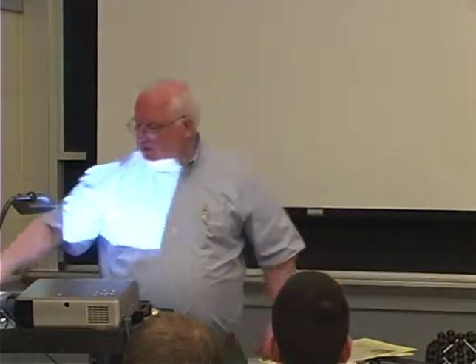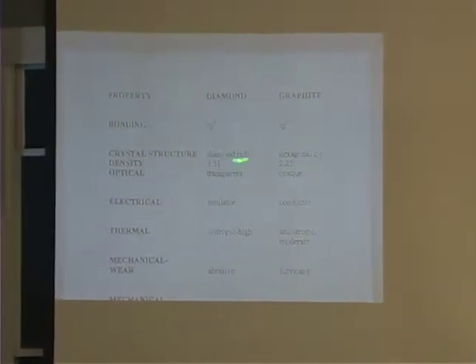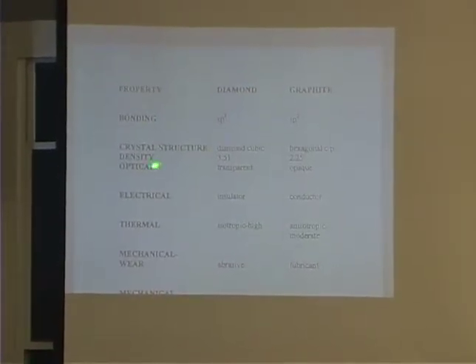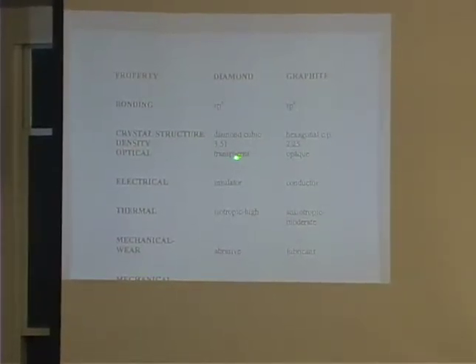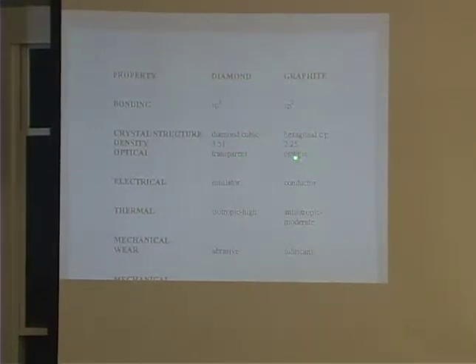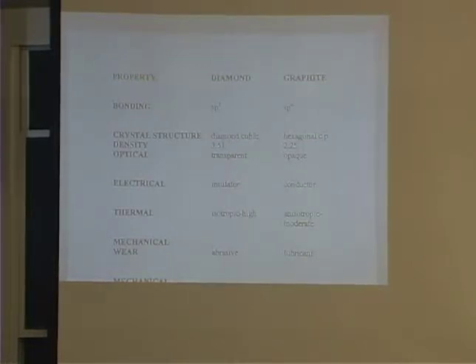Okay? That difference in bonding makes tremendous differences in the properties of these. So the bonding in graphite is sp2, diamond is sp3. The crystal structures are different because they reflect the geometry of the bonding. The density is different. Whether they're transparent or opaque differs too: diamonds are transparent to visible light. Actually, diamond is transparent further into the infrared than any other crystal we have. And so if you're using really fancy, very long wavelength infrared, you sometimes have to use diamond windows on your detectors. Not because they're hard or because they're expensive, but because they're transparent down to about 50 microns, and there's nothing else that goes below about 40 microns.